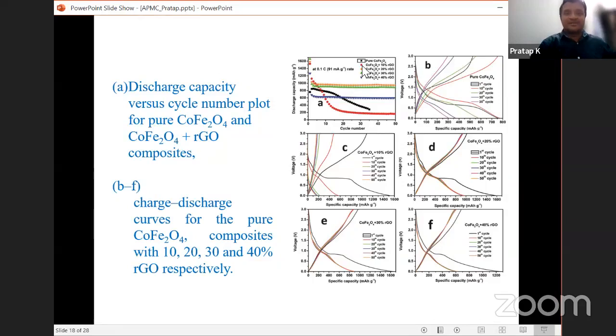The red one is cobalt ferrite with 10%. Cobalt ferrite with 10% is initially showing good charge, but only after 15 cycles it is coming back and losing all its charge. So look at the orange one, cobalt ferrite with 20%.